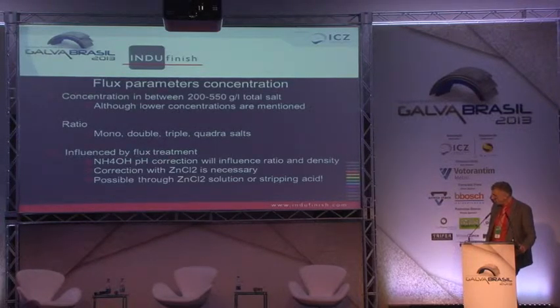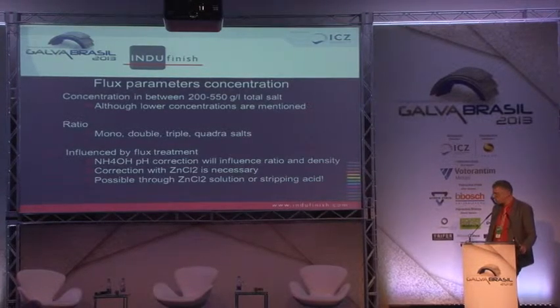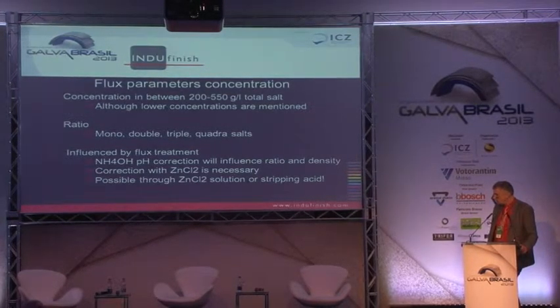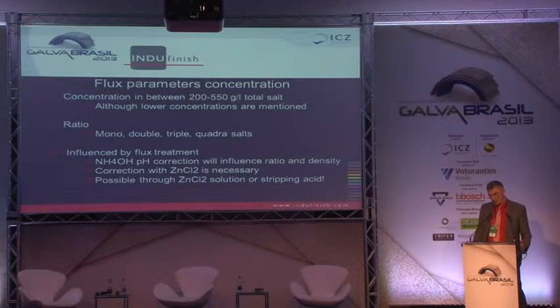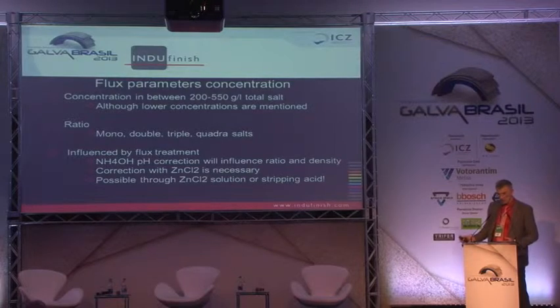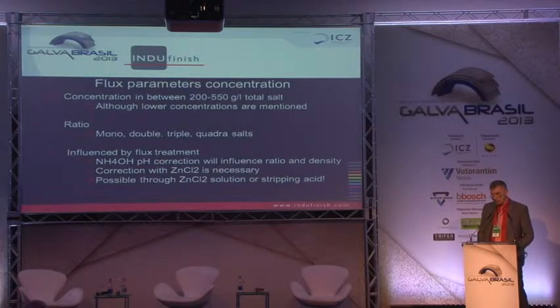Parameters on concentration. Western Europe, not the UK, is using flux at about 400 grams a liter. The UK is using 200 grams a liter. And this ammonium hydroxide that we are using to keep up the pH will influence your ratio and density. Therefore, we will need zinc chloride, because the goal is actually to get a never-dump system. We want to install the flux cleaner, we will service your fluid, and you're ready. You only have to buy standard chemistry, as in hydrogen peroxide and ammonium, and that's it.